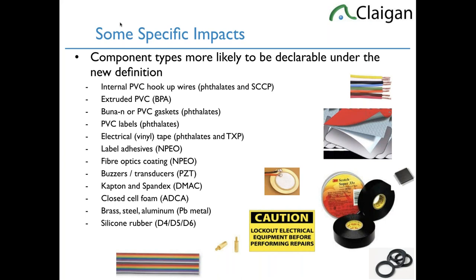The EVA foam and polypropylene foam, or whichever, has all these little closed cell pockets in it for the nitrogen gas being released by the ADCA being consumed. In the initial mixture, the ADCA is about 20% of the weight of the EVA material. Once it's fully foamed, most of it should be reacted away, but there's not great stats on it. So considering it starts at 20%, usually it might be still above 0.1. It's an interesting problem and not well documented.